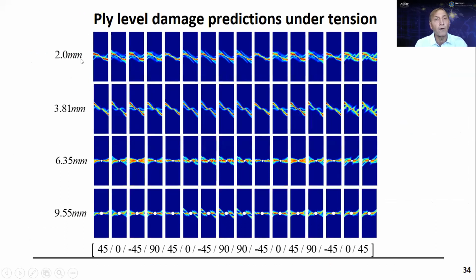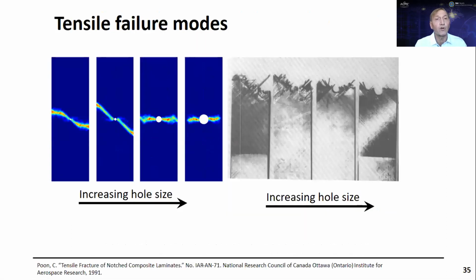So here, as you go from a smaller hole size to a larger hole size, the slanting sort of becomes more perpendicular to the direction of the applied load, pretty much for each ply that you see here. We're applying the same critical stretch criteria. We're not changing anything. The only difference is the size of the hole. And if I superimpose all of these plies on top of each other, from a smaller hole size to a larger hole size, you see it captures the experimentally observed behavior. As the hole size increases, the nature of the failure changes.